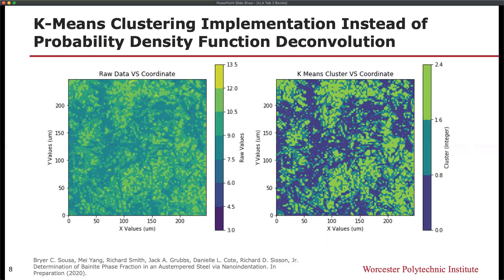Rather than using probability density functions, one can also consider k-means clustering, which is a form of machine learning or sophisticated statistical analysis, wherein spatial information can be retained and phases can be identified as a function of the cluster they belong to. Here we see raw data in terms of the hardness values and the x and y coordinate points associated with the mechanical maps, and the resultant k-means cluster phase identification, wherein one phase is associated with the austenite or low-carbon martensite, another is the bainite, and the other is the high-carbon martensite.